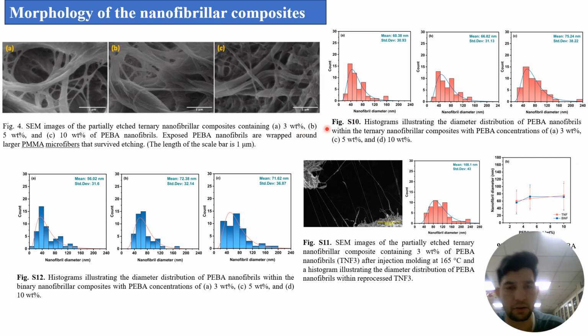Figure 10 shows the histogram of diameter distribution. The distribution of PEBA nanofiber diameter in the ternary nanofiber composite ranges from 20 to 230 nanometers. The average diameters are 60 plus minus 30, 66 plus minus 31, and 75. These images show the size a little bit more clear and zoomed, so that's why I can see.